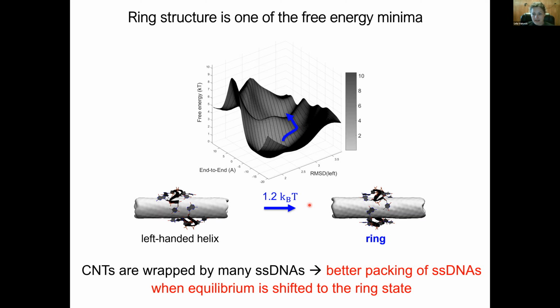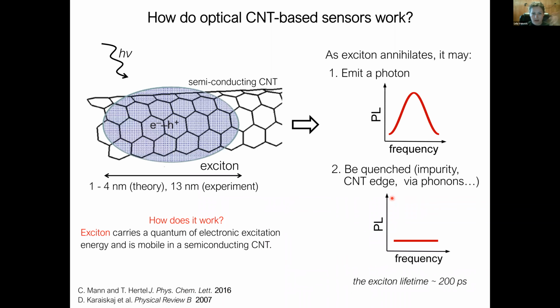And then the question is, why is the nanotube wrapped by these rings very dark, not emitting light, which is what experiments observed? We know now that nanotubes wrapped by GT6 are wrapped by these rings. So why are they not emitting light? Initially they don't emit light. Once you add dopamine and it binds to the nanotube, they start emitting light. To understand the effect of these rings on the light emission, we need to briefly mention the mechanism of this light emission.